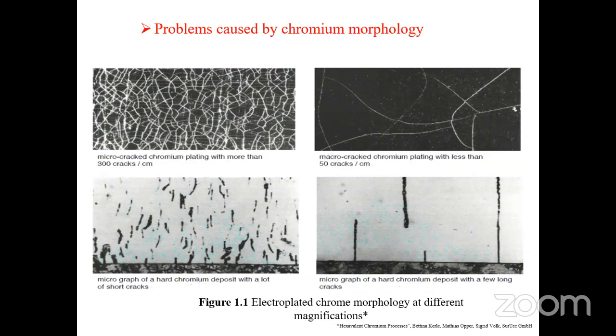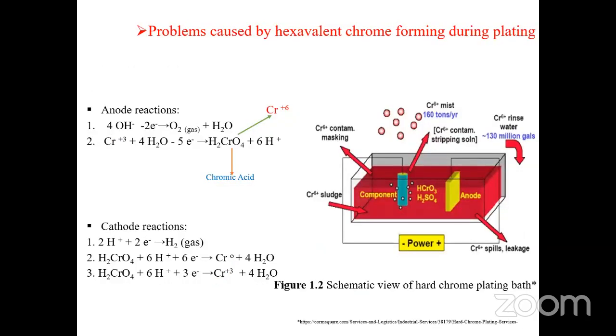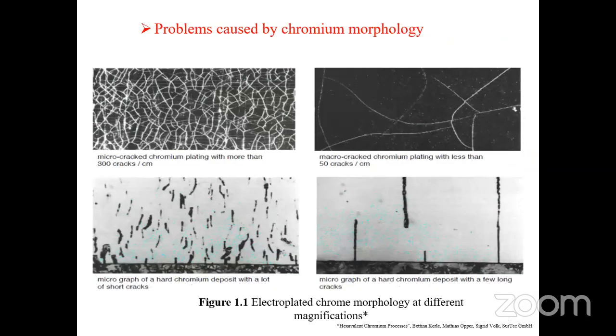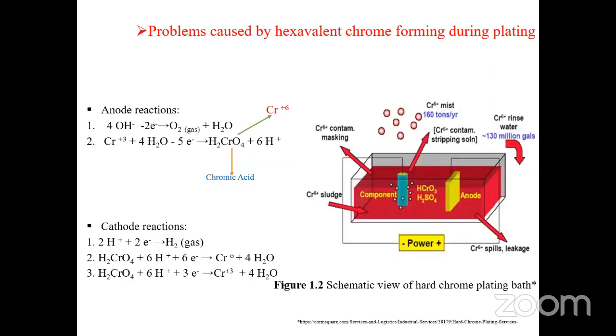Hard chrome plating is often used in applications where the parts are subject to very high wear and a thicker chrome layer is required. But excessive thickness results in cracks and larger pore structure in the chrome surface.